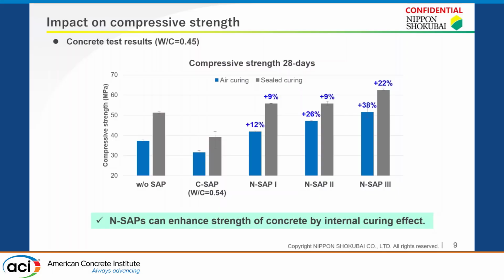This slide highlights the impact of our new SAPs on the compressive strength. We compared the compressive strength after 28 days. When conventional SAP was used along with extra water, there was a significant decrease of compressive strength. In contrast, our new SAPs show strength enhancement compared to the control mix without any SAP.